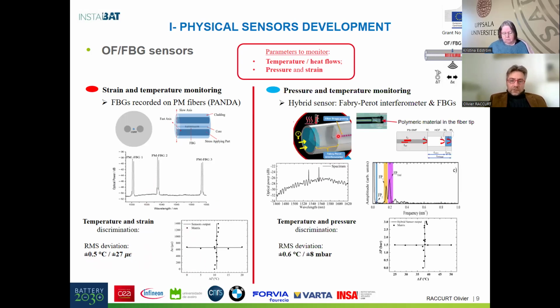And another kind of sensor developed during the project is a hybrid sensor, because we add into the FBG sensors a Fabry-Perot cavity to monitor the pressure at the same time as monitoring the temperature. With this kind of sensor, we can measure the pressure and the temperature at the same time. The Fabry-Perot cavity gives some wavelet in the signal, and the shape of the wavelet depends on the pressure applied on this cavity. And the temperature was monitored by the FBG peak, you can see here. And in the same way as the previous sensor, we can decorrelate the two signals, and there with an accuracy of 0.6 degree and 8 millibar for the pressure.